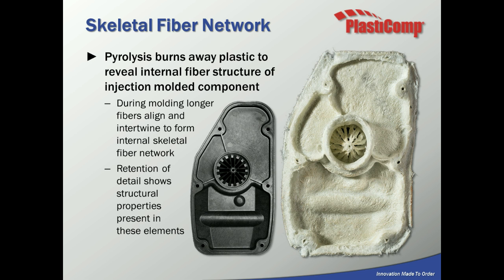Along the perimeter of the part, you can see thicker sections near the screw bosses. And those thick sections are filled with glass as well, and because of the low consistent shrink, we don't see voids or warp in those areas. So now with long fibers, it gives designers flexibility in part design to moderate or change wall thicknesses from thin to thick.